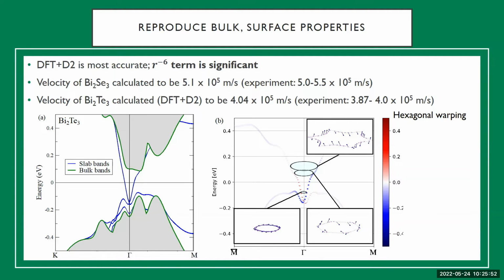And we were able to reproduce the Dirac velocity, which I'll talk about in a minute. The Dirac velocity of these topological surface states quite accurately for both bismuth selenide and bismuth telluride. And we were also able to obtain what's called the hexagonal warping in the surface states of bismuth telluride.